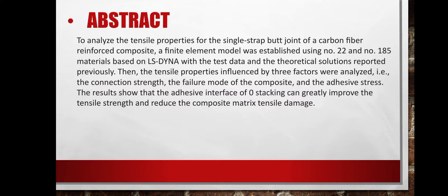with the tested data and the theoretical solution reported previously. Then the tensile property influenced by three factors were analyzed, that is the connection strength, the failure mode of composite, and adhesive stress. The result shows that the adhesive interface of zero stacking can greatly improve the tensile strength and reduce the composite matrix tensile damage.